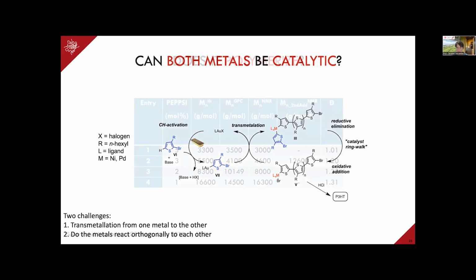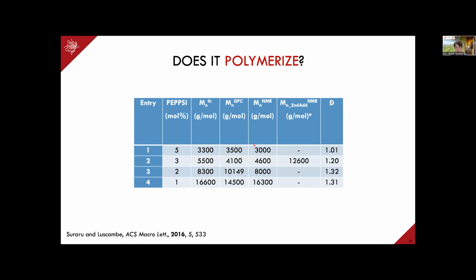First of all, does the polymerization work at all? Here I'm showing some molecular weights. So yeah, we do get the polymerization to occur. There are other questions too, though. Was it controlled? Were we getting controlled molecular weights? And you can see from the theoretical molecular weights by GPC and NMR, we're getting relatively good agreement. So it is controlled. We can target a molecular weight and get that molecular weight.